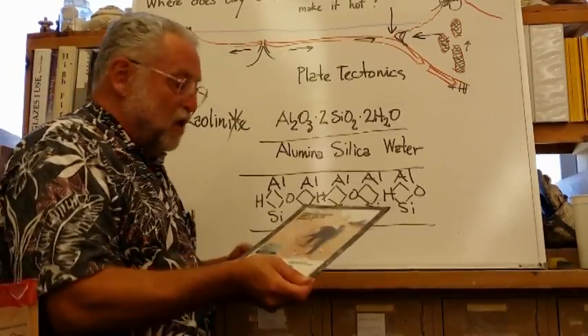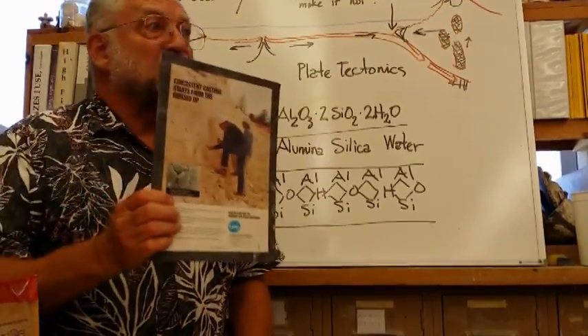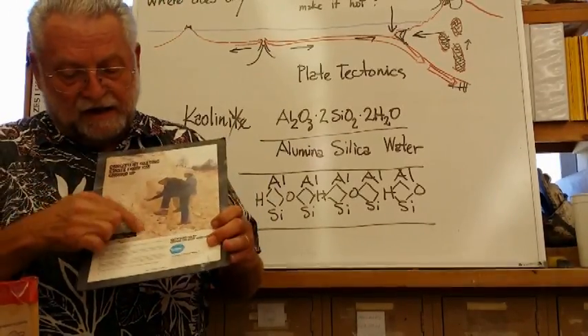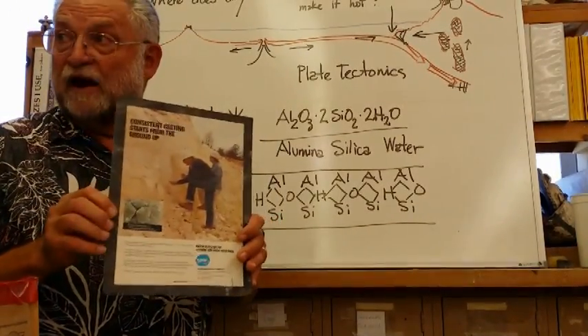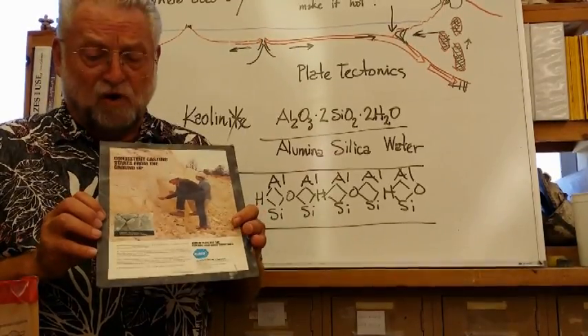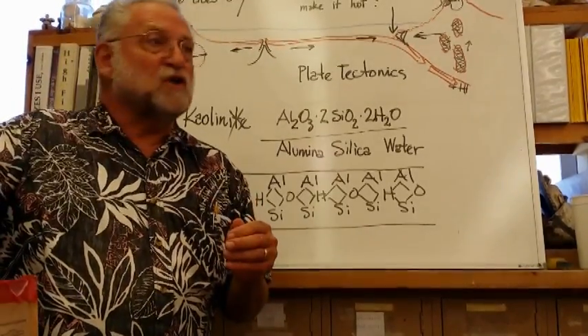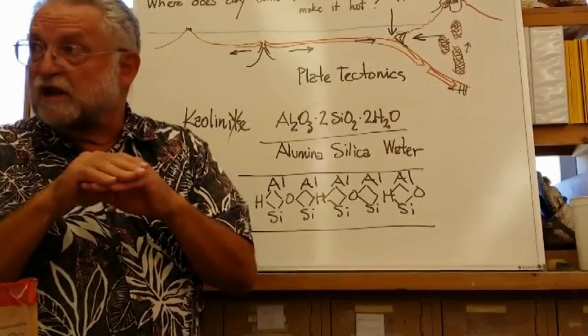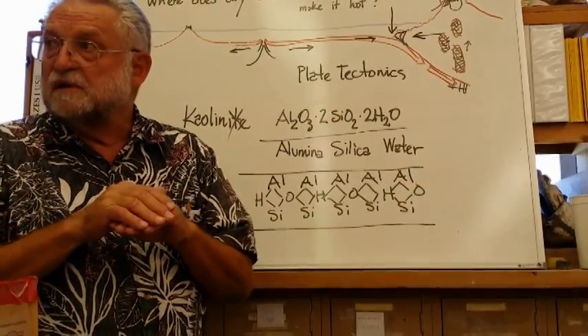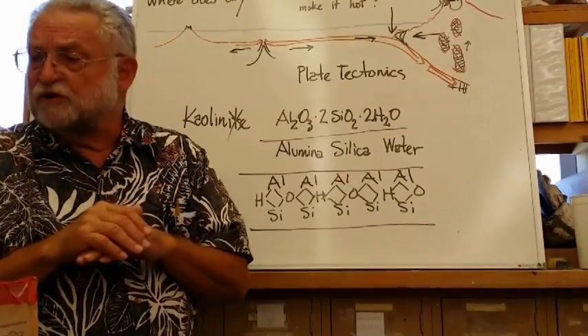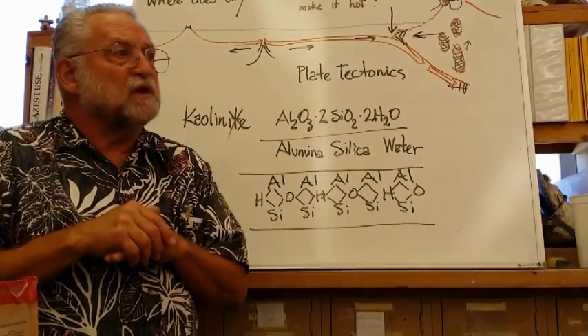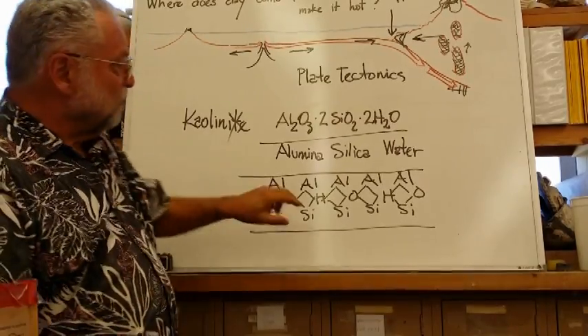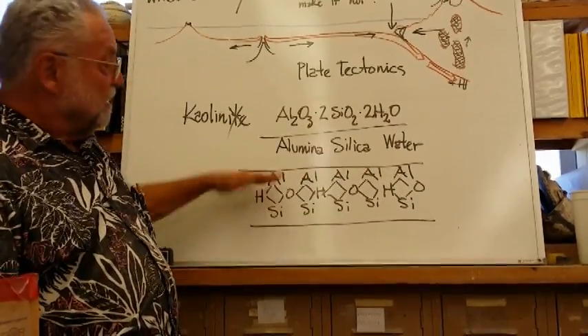I said these are very small, so in this kaolin advertisement from Albion, Georgia, right here we have an electron micrograph that's 25,000 times normal. And if you look at that, you'll see that the basic structure of clay particles is flat and plate-like, which has all kinds of mechanical implications for us as we work with clay. But the source of that flat plate-like structure is this arrangement of aluminum and silicon atoms bound together by those ions of hydrogen and oxygen.